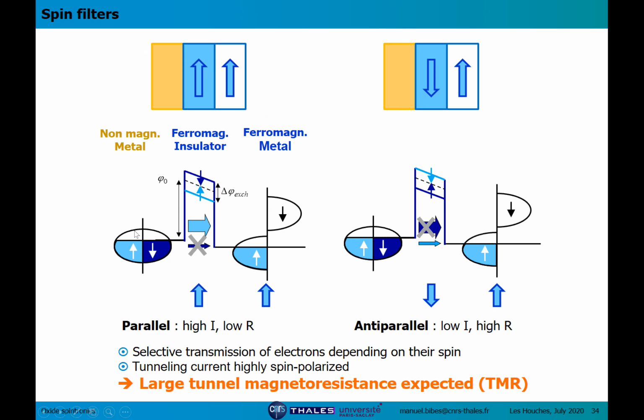So when electrons are tunneling from the non-magnetic metal across the ferromagnetic insulator, they are going to see two different barrier heights, depending on their spin. Because, as I told you, the barrier height is related to the band gap somehow. And in a ferromagnetic insulator, you have exchange splitting of the bands, and you would have a different value for the band gap for spin up and for spin down. So you will have different barrier heights for spin up and for spin down, and so you will filter out electrons depending on their spins.